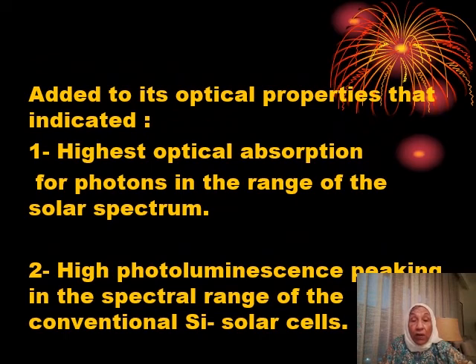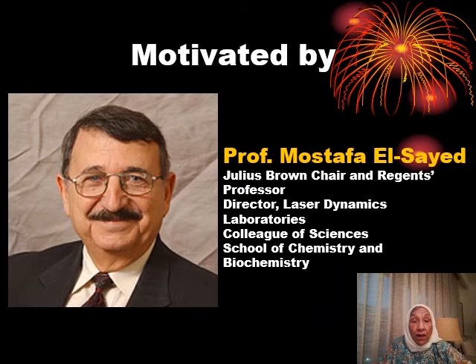Added to its optical properties that indicated highest optical absorption for photons in the range of the solar spectrum, high photoluminescence peaking in the spectral range of the conventional silicon solar cells, and this would be our successful utilization of the conventional cells that exist on the market nowadays, with adding the new nano structures we prepared by the liquid phase laser ablation technique.